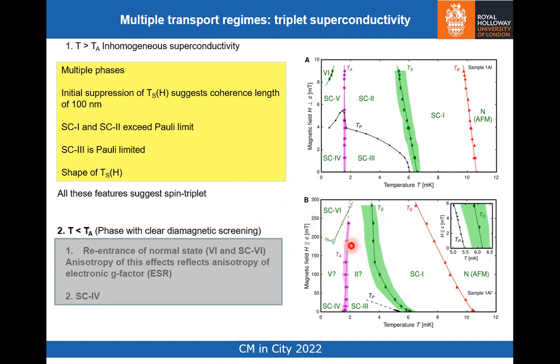So then what about at temperatures less than TA? This is over here. We see re-entrance of the normal state for both field orientations. It happens at a much lower magnetic field, around 10 millitesla for field in the ab plane, whereas it's only kicking in at about 200 millitesla for fields along the c axis. And even then, actually, the resistance doesn't fully recover the normal state value. But that anisotropy in the re-entrance of the normal state is kind of understandable in terms of the anisotropy of the electronic g factor for those two orientations.